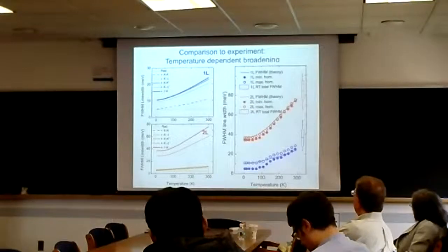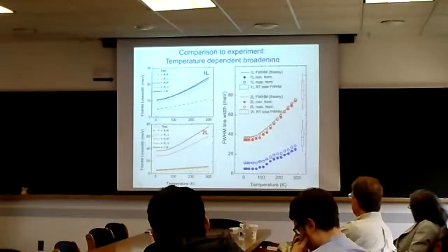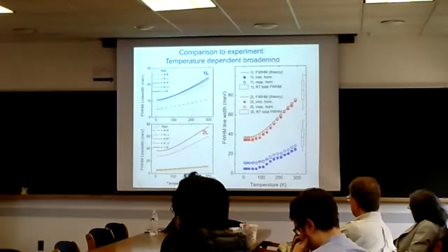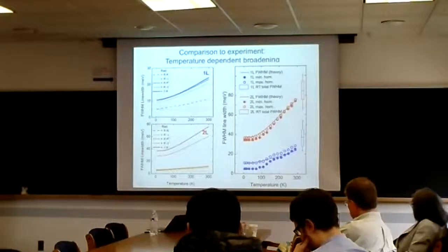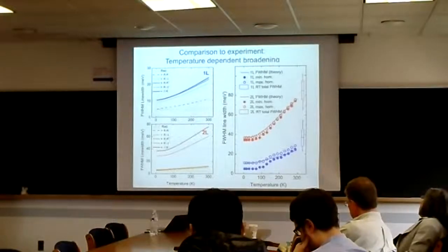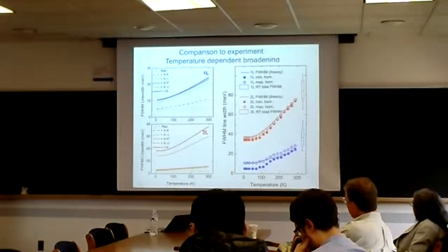In fact, when we plot the total line width from the theory on top of our experimental temperature dependence, what we see is that this is in fact what's going on. If we didn't include this channel of the new dark states that arose from screening interactions, we'd be missing about 30 meV or 40 meV in each of these cases.